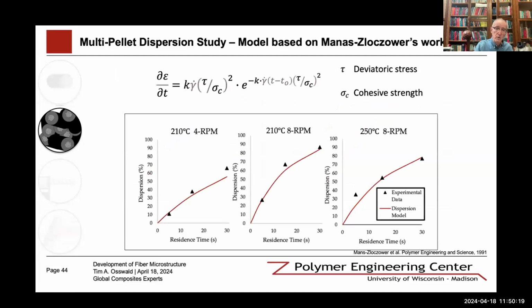Then what we did is we borrowed a model from Professor Manas-Zloczower, which was a dispersion of carbon black using the cohesive stresses and the stresses during dispersion. And we found that the model actually worked quite well in predicting the dispersion at different conditions, 210 degrees at 4 and 8 RPM, and then 250 degrees and 8 RPM. So varying the temperature, which varies the viscosity, of course, and varying the RPM. You can notice again here we're still using relatively low RPMs in our Couette device, but you can see the model compares well to the experimental data.